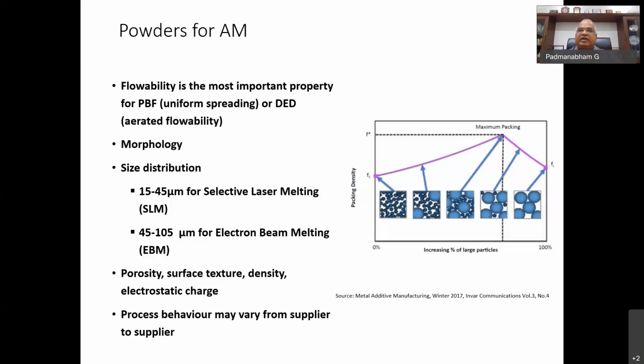And when we have melted and solidified, what we are looking for is 100% density in the part. For that, you need the right kind of combination of bimodal distribution of these spherical particles. What you see in the graph here is that the packing density should be highest. What you see here is a combination of particle sizes, which will decide the range of size, the size distribution of particles that you should choose for an SLM method or an electron beam method. Because in electron beam, we have already seen if it is too fine, the vacuum can cause problems, and then the problems of electrostatic charge can also come up.